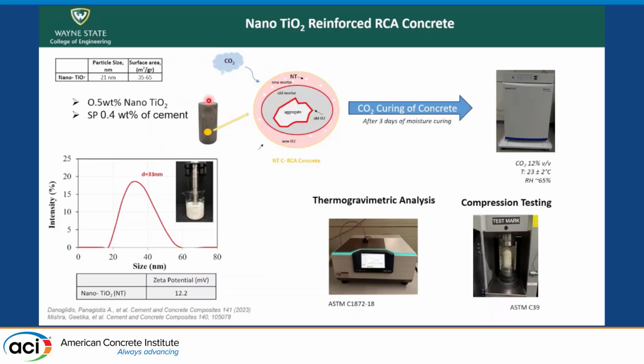We created concrete cylinders that we introduced into the carbonation chamber after 3 days of moisture curing. We followed the same procedure that Professor Gonsta previously described in her presentation. So we cast concrete cylinders, let them moist cure for 3 days, and then transferred those samples into the carbonation chamber. We applied a CO2 concentration of 12% for the remaining 25 days until the samples reached 28 days of age.